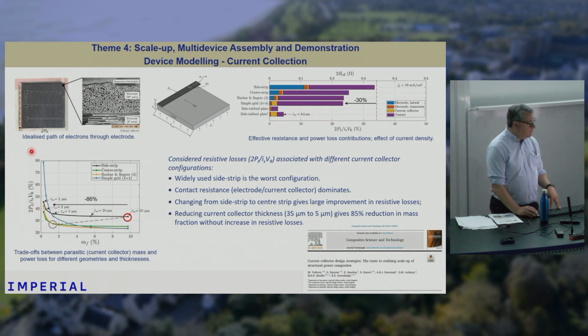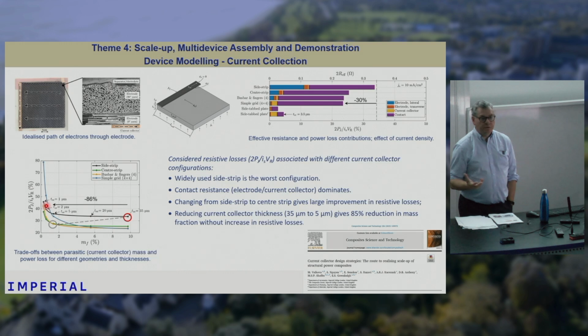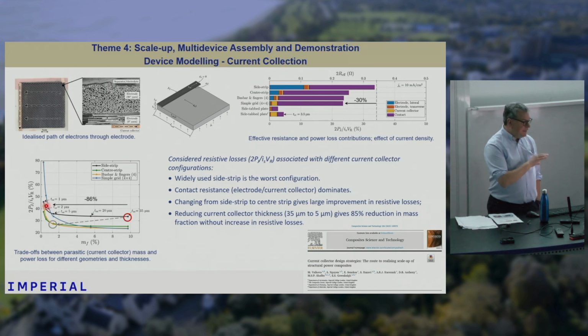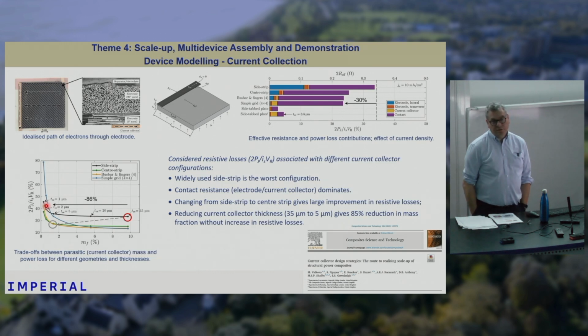So the higher this number, the more losses we're getting electrically. The copper tape we're using at the moment is 35 microns. But we recognized if we could make that down to 5 microns, then rather than having almost 10% of the mass, it would be less than 2% of the mass of the device. So we could get a weight saving without any significant increase in the resistive losses. So there are some strategies here that could start to give us improvements in the current collection without adding lots and lots of mass to the device.